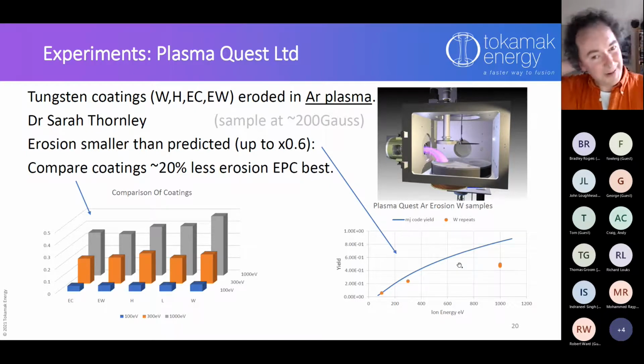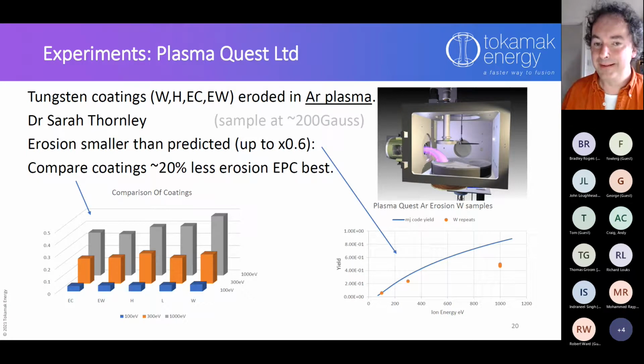This is probably because of the magnetic field. This is 200 Gauss, so there's a fair magnetic field in here. And this is very interesting because we've of course got electromagnets confining our plasma, so we have magnetic fields in our tokamak. And in the literature there is something called prompt redeposition, which is basically when you're sputtering off material from your sample, if it becomes ionized, it's then subject to a magnetic field, and it can basically be turned round by the magnetic field and pushed back onto the sample and redeposit.